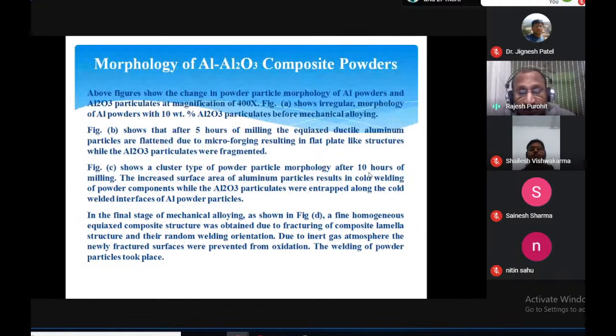The figures show the change in powder particle morphology of aluminum powder and aluminum oxide particulate at a magnification of 400. The first figure shows the irregular morphology of aluminum powder with 10 weight percent of aluminum oxide particulates before mechanical alloying, when mechanical alloying is not started. The second figure shows that after 5 hours of milling, the equiaxed ductile aluminum particles are flattened due to microforging, resulting in a flat plate-like structure, while aluminum oxide particles are fragmented.